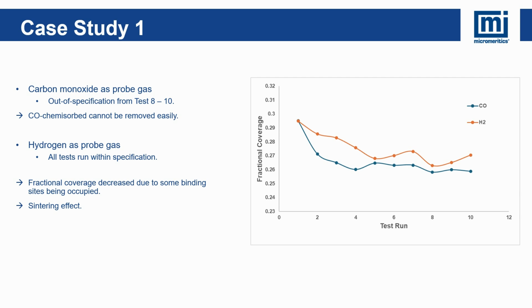It is a good indication that sintering effect took place on our catalyst, meaning platinum particles migrated and formed a cluster of larger platinum particles on the support. Some active metals became embedded in the cluster, and only a small fraction of metal participates in the reaction.